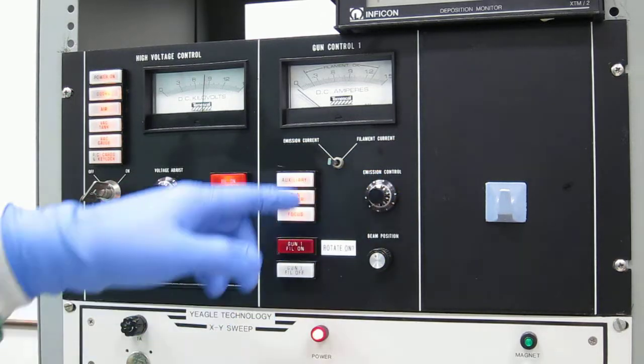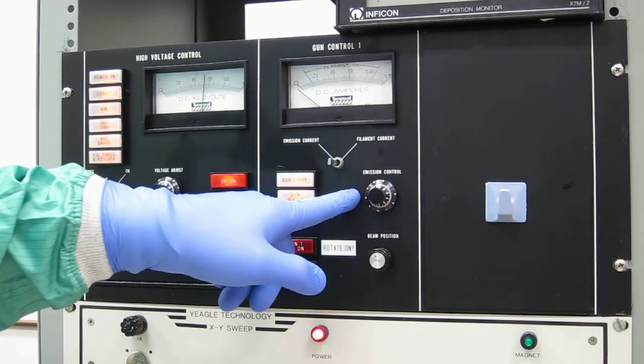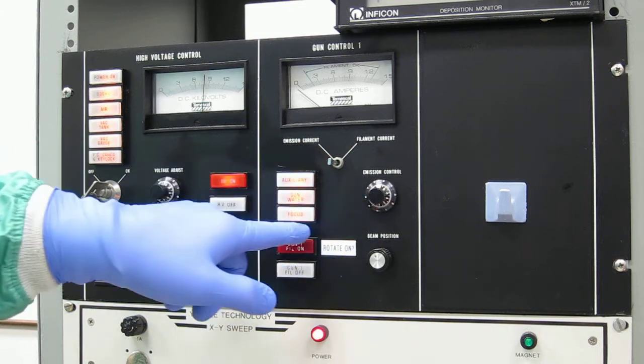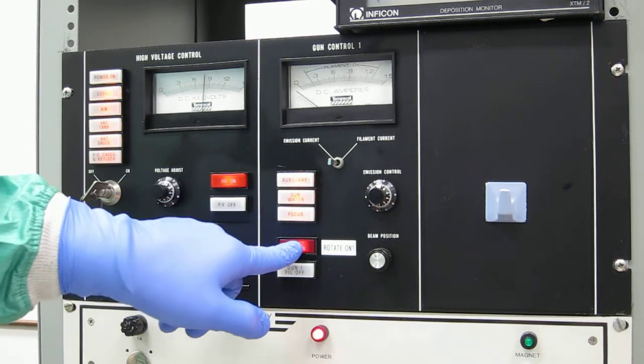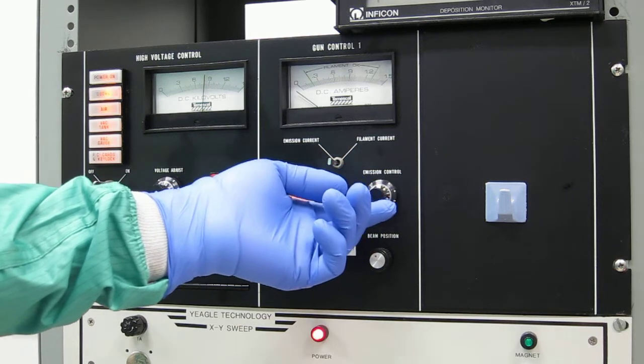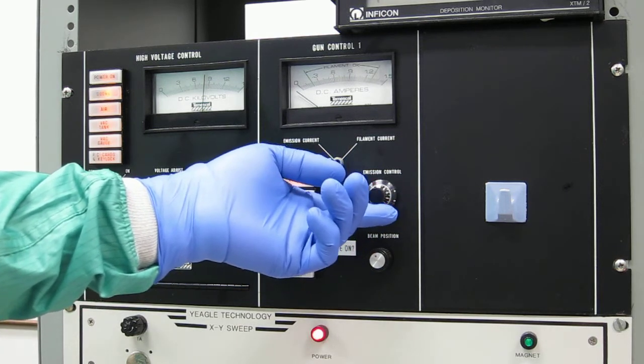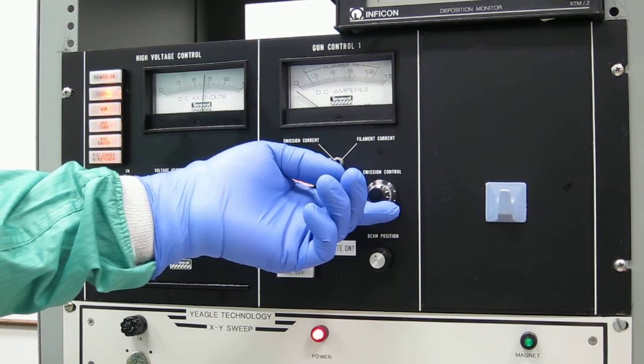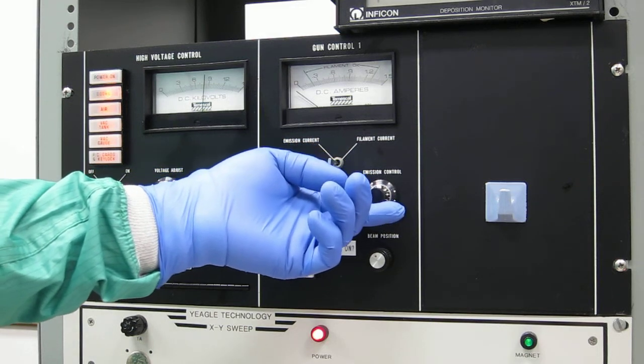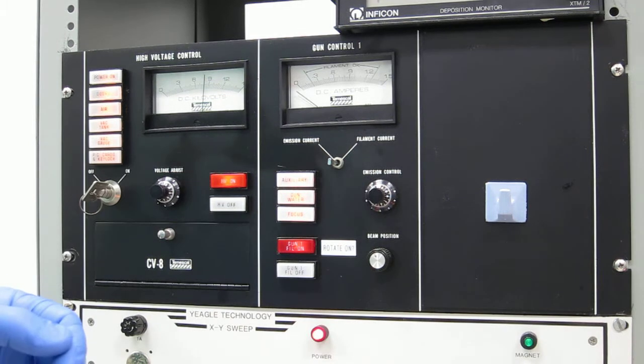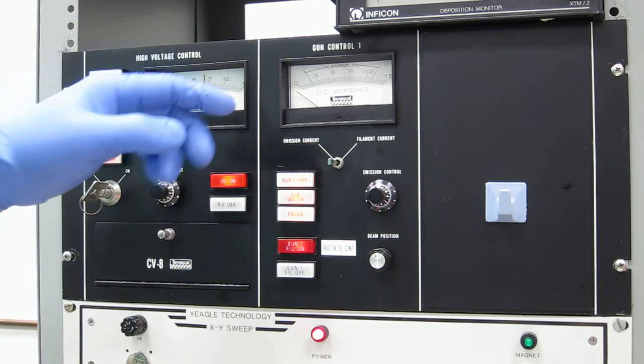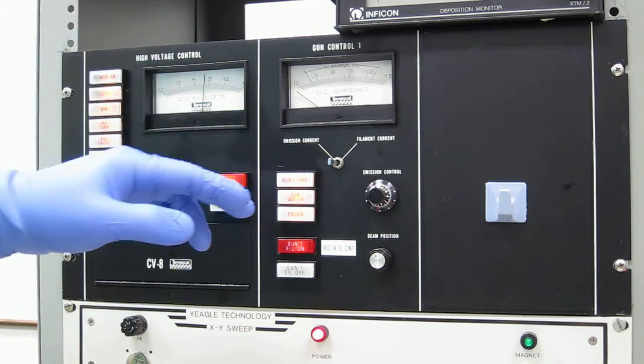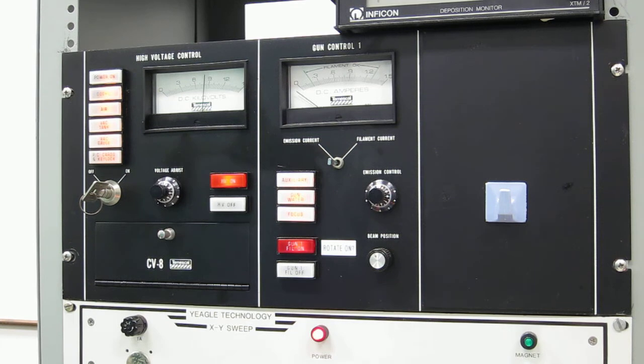The actual deposition is controlled by controlling the filament current. We start the filament with 0 and slowly increase the filament current until a beam appears on top of the crucible. Once that beam appears on top of the crucible, it'll begin to melt the material inside. At that point, we adjust the XY sweep underneath in order to center it on top of the crucible, and then we control our deposition rate using the emission control right here.